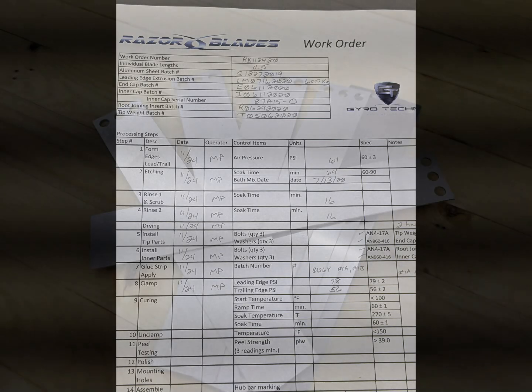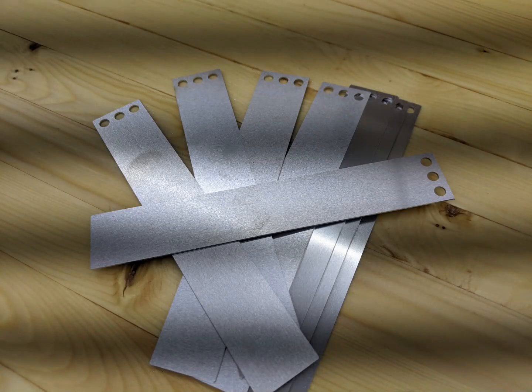At the same time, we produce a set of coupons. These are produced from the same lot of sheet metal, use the same lot of adhesive, and they were etched along with the blade components and cured in the same heat cycle as each blade.